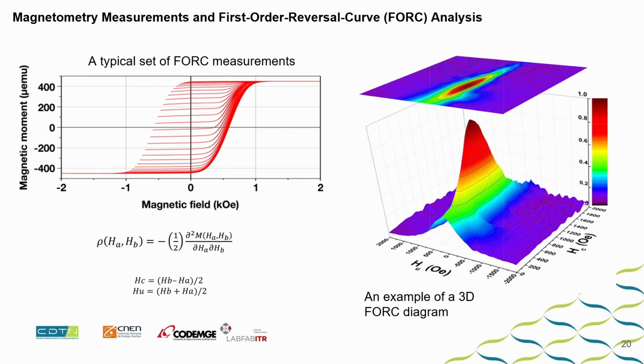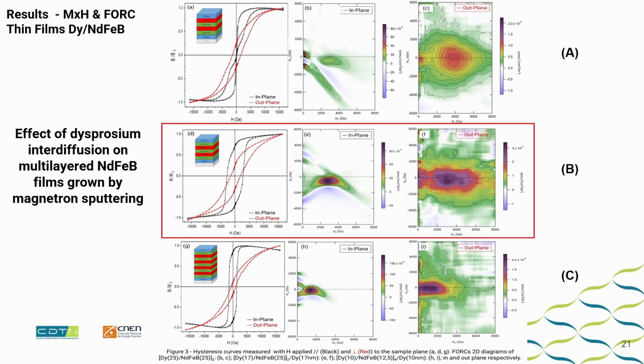measure. From the magnetic measure, we can extract the different phases inside this kind of multilayer structure. And it's more important to show here that we have 2 layers. This structure shows us 2 kinds of soft layer in these states when we measure this permanent magnet with the magnetic field applied in the plane of the multilayer. And here we found almost this kind of boomerang shape, and this is almost 3,000 Oe coercive field. And there is the importance of studying this interdiffusion process.